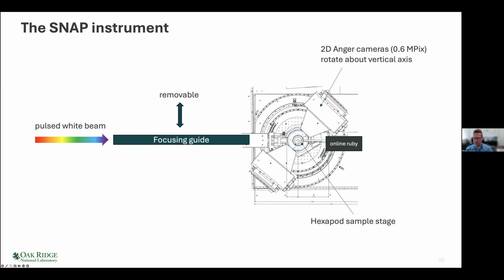The sample position is right here, and that sits on a hexapod, which is just a multi-axis but very high precision and high load bearing stage. And then about that same axis, we have 2 detectors, which in our case are called Anger cameras. A lot of this is shielding. You can think of the camera as being essentially a flat grid of active pixels, and each camera has 600,000 pixels. So we have 1.2 million in total. And then we have a nice online Ruby system, which we can translate in and out of the beam to check the pressure using Ruby fluorescence.